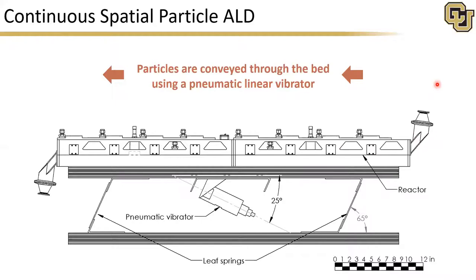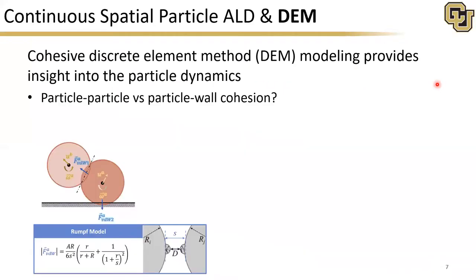There are some aspects of the particle motion that are difficult to investigate experimentally, so we developed a cohesive discrete element method model to provide insight into the particle dynamics, in particular in two key areas. The first is to investigate the role of particle-particle and particle-wall cohesion. Typical studies on vibratory convection have focused on coarse powders where cohesion is often neglected, but in particle ALD, where we deal with fine Geldart A and even ultra-fine Geldart C powders, cohesive forces play a significant role and cannot be neglected.